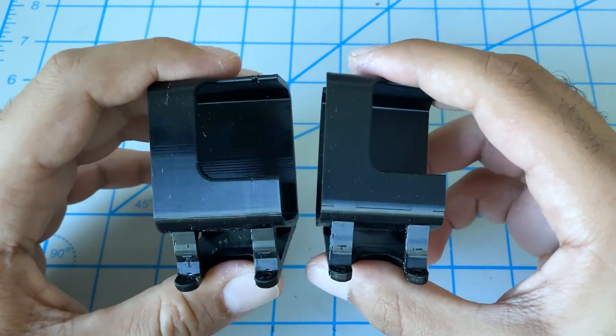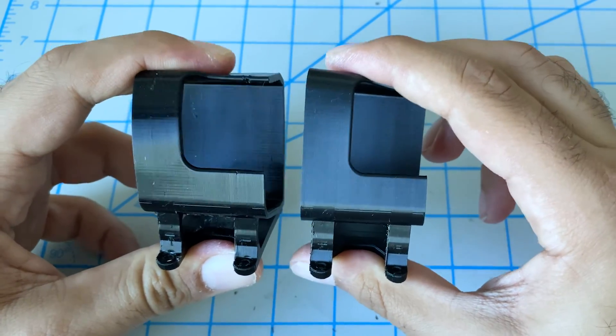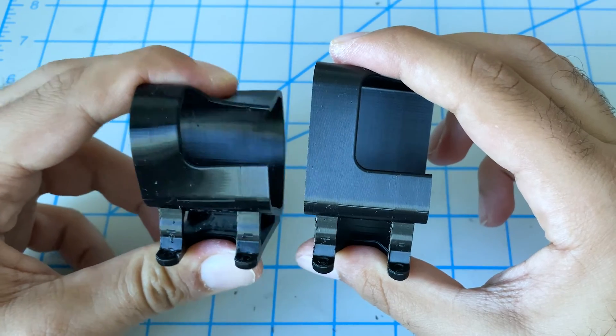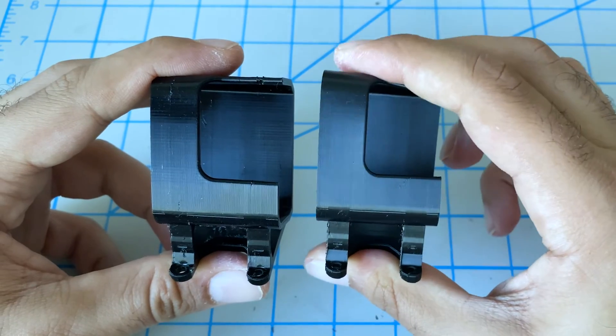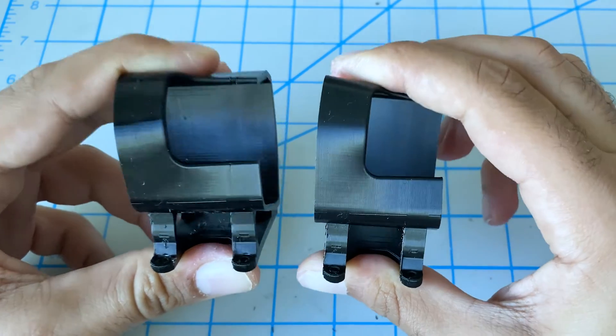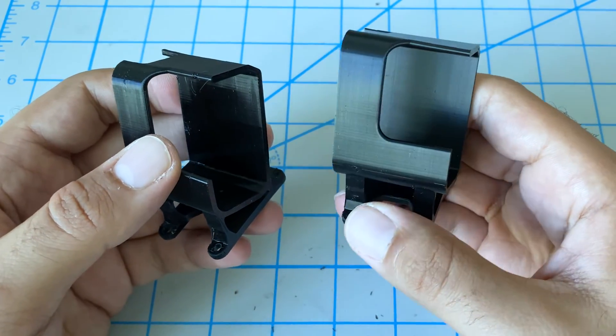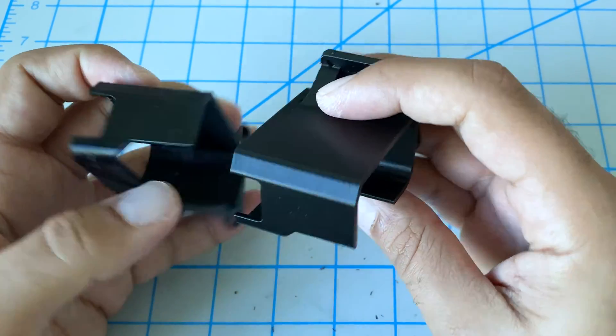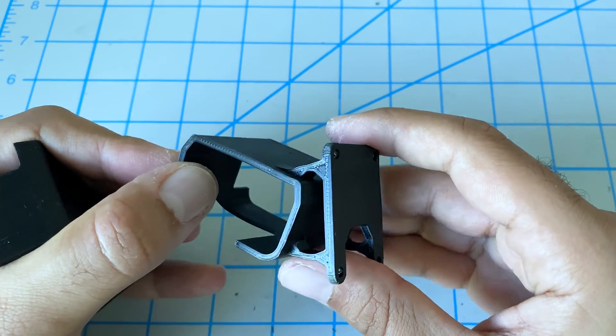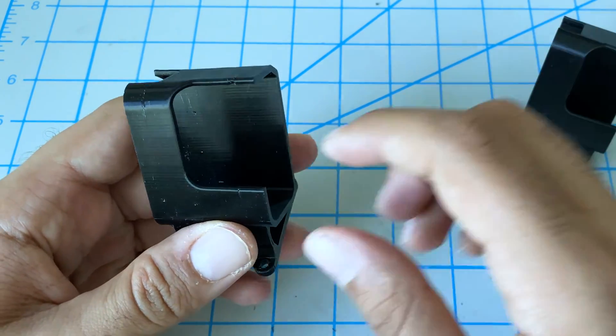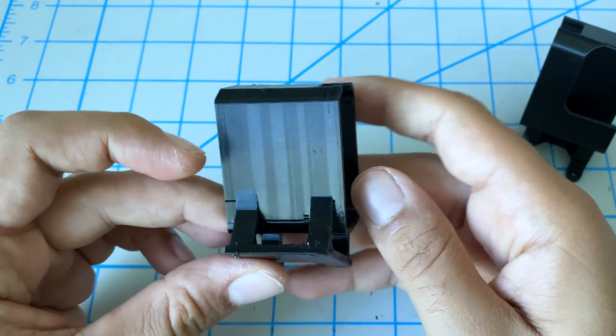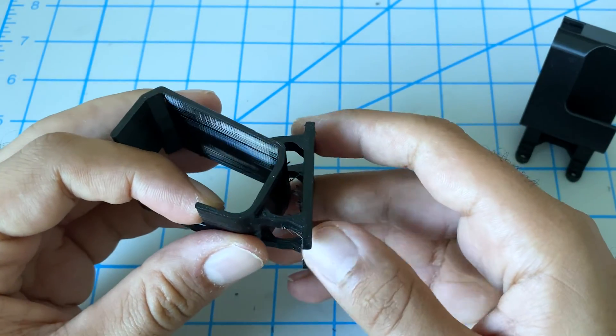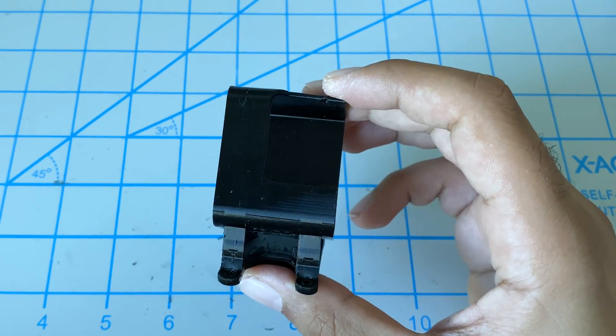And the biggest difference, just check this out, is how soft they are. So I'm giving about the same kind of pressure on each of them. We can see the SainSmart is very elastic, very flexible, whereas the Priline is a lot stiffer. So if I try to squeeze as much as possible, we can see a difference here. And then the other piece to bear in mind also is the Priline being harder, it's also easier to print. So we can see not too many imperfections. It printed very well on the Ender 3.